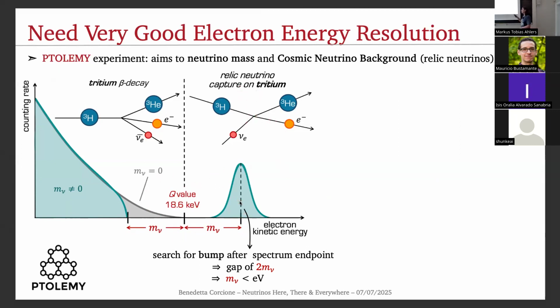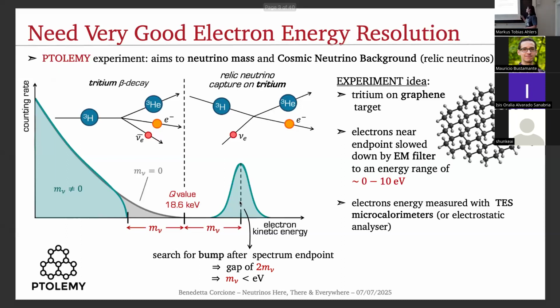Now, these modifications are equal to the value of the mass of the neutrino, so we're talking about milli-electron volts. That's why having an excellent energy resolution is crucial to try to distinguish them in this final spectrum. And the idea of Ptolemy is to load the tritium on a solid-state target made of graphene, and then slow down the electrons coming from the beta decay and the relic neutrino capture, and finally measure their energy. One of the options is with transition edge sensors. So this is the framework.